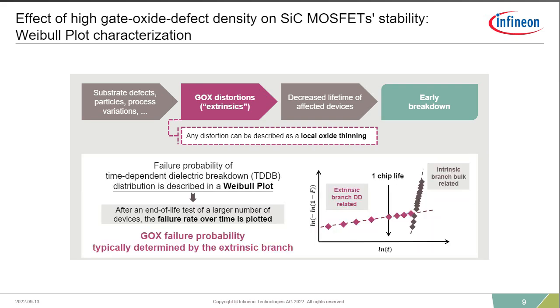So just going back here to the structure, what we see here is a Weibull curve, and along the x-axis you have your time to failure, and on the y-axis you have the rate of failure. The further you move to the right of this curve, the longer lifetime and reliability you have of a product, until the point where you reach this intrinsic branch. And the intrinsic branch is basically the wear out of the device. This could be 50 years, 25 million cycles or something to that nature, where it basically is a limitation of the material itself. So most of the time you're operating in the extrinsic branch here.